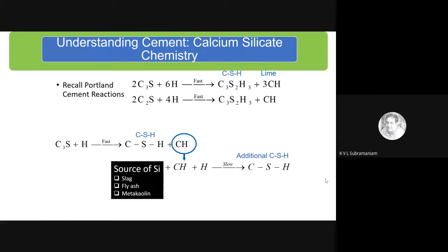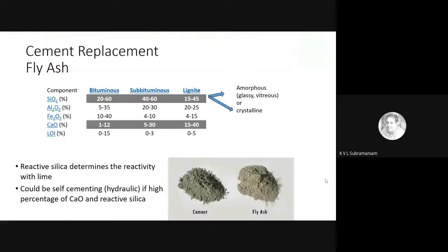So again, it goes back to having a system which has calcium and silica, and we are bringing in additional silica from these materials. And fly ash, if you look at the oxide composition of it, depending on the clay that is burnt to make the fly ash, contains a variable amount of silica, SiO2. That is the primary ingredient that we count on when we are looking to replace